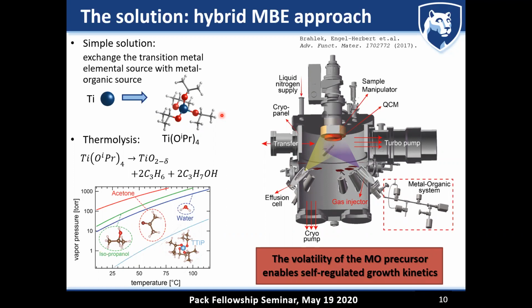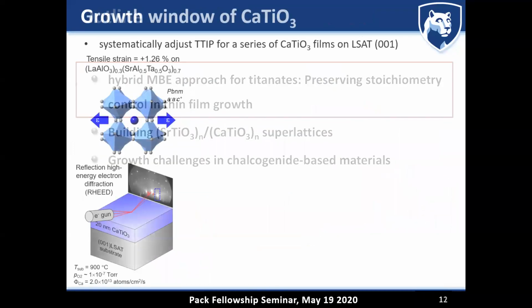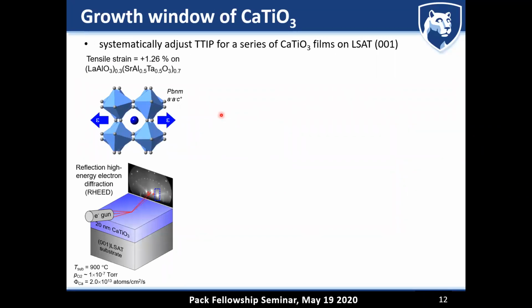Thank you, Doctor, for your presentation. I just have a question regarding the calcium flux. What the composition and what the growth temperature that you used? So growth temperatures, I don't know what the specific growth temperature was. Here you go. The growth temperature we used was 900 degrees C. That's measured by the thermocouple of the substrate holder. And the calcium flux that we used was measured by a quartz crystal microbalance. And we supplied 2.0 × 10^13 atoms per centimeter squared per second.